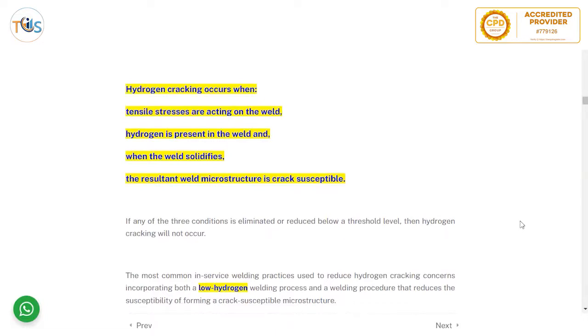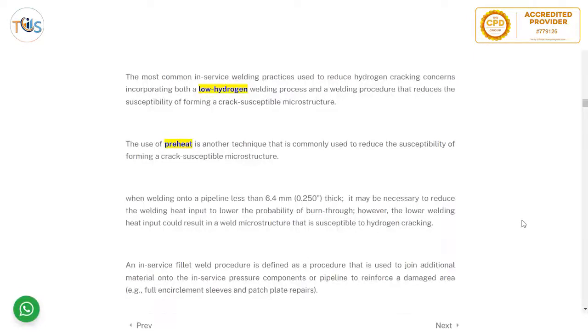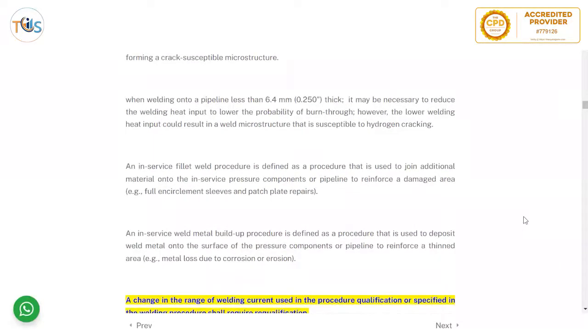So if any of these three conditions is eliminated or reduced, then hydrogen cracking will not occur. The most common in-service welding practice used to reduce hydrogen cracking concern is obviously using a low hydrogen welding process. So you're reducing the amount of hydrogen, and using a welding procedure that reduces susceptibility of forming a crack susceptible microstructure. Use of preheat is another technique commonly used to reduce the susceptibility of forming a crack susceptible microstructure. When welding onto a pipeline less than 6.4 millimeter or 0.25 inch thick, it may be necessary to reduce the welding heat input to lower the probability of burn through. However, the lower welding heat input could result in a crack susceptible weld microstructure.